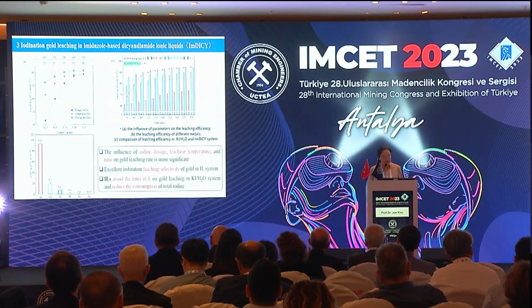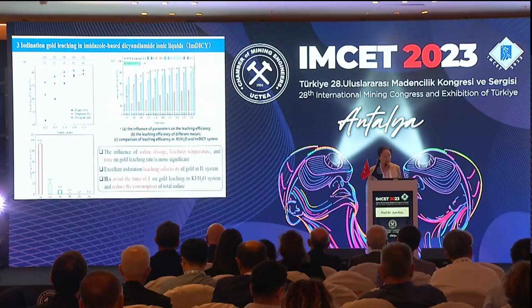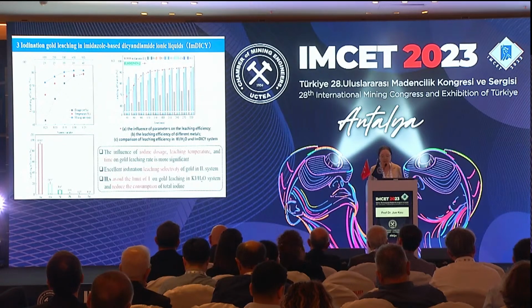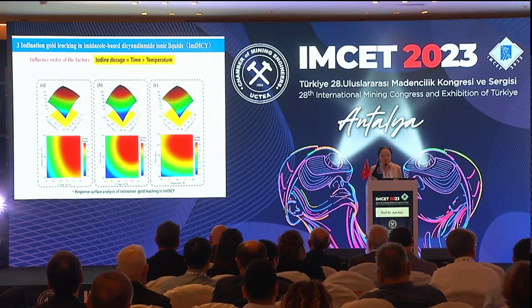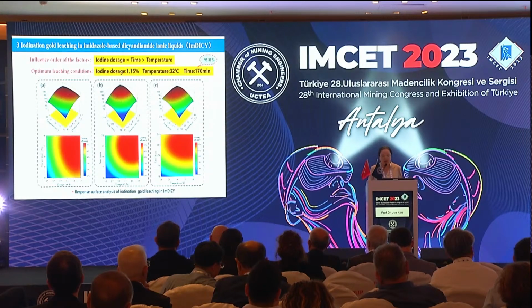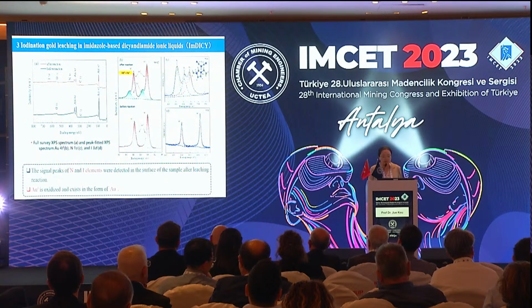And this is the comparison of the leaching rate of different metals, including gold, copper, nickel, lead, and iron. Here we can see the gold has the highest leaching rate of 93%. Copper is 20%. It shows a better selectivity in the leaching process. This is also the comparison of different iodine dosage, time, and temperature. I'm going to skip this page. The best condition is right here.